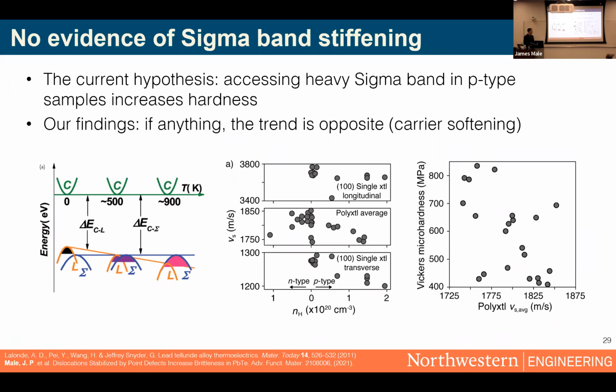If this were the case, we should see the sound velocity increase with P-type carrier concentrations. And in fact, we see, if anything, a subtle decrease in sound velocity when we dope our materials P-type, and also when we dope them N-type, which may be due to charge carrier softening. But essentially what this shows is that hypothesis is just wrong, and we need to figure out what's actually going on to make these materials brittle.